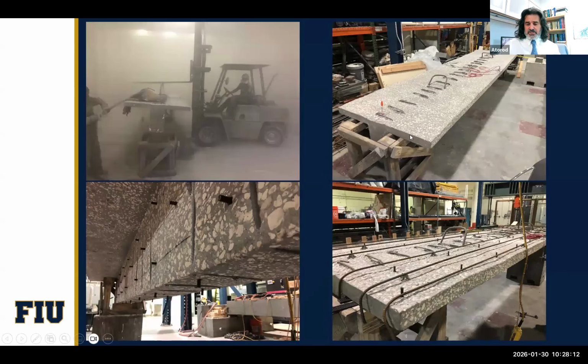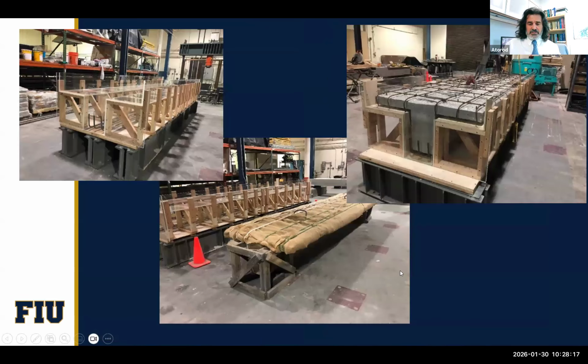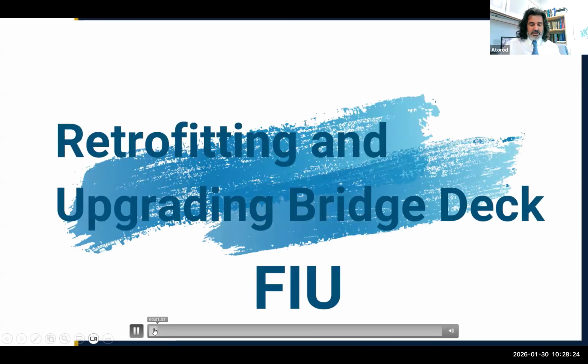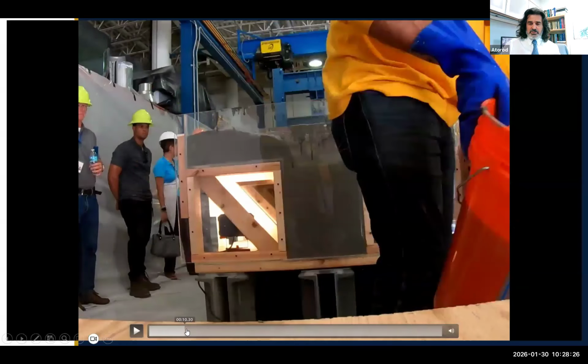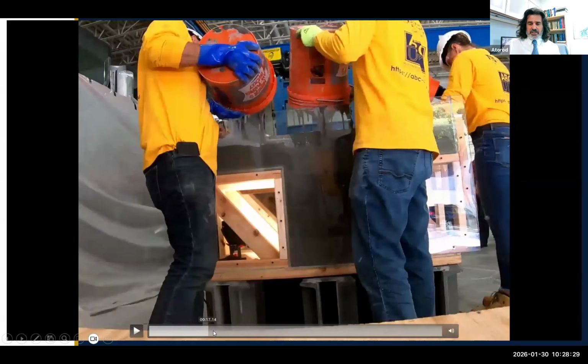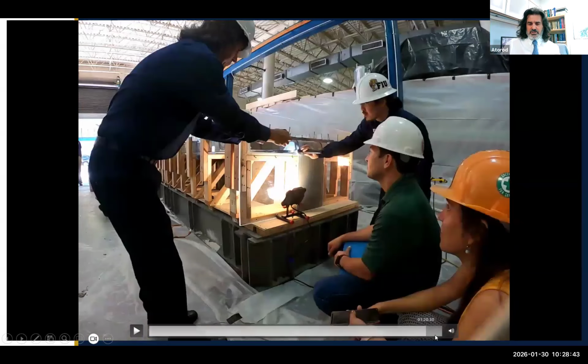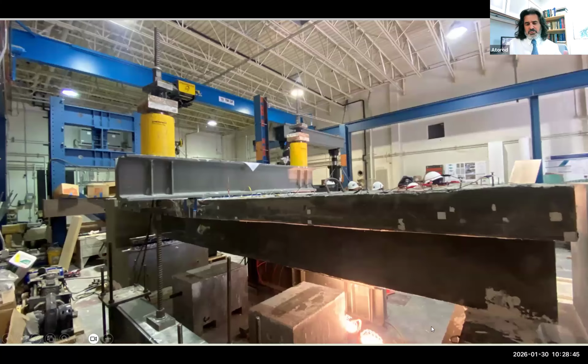Here is the T-beam, and we sandblasted it, put in additional reinforcement, and then put in the epoxy glass formwork. I can show you here: you can see we pour the UHPC, and it flows into a very small area. Because it was a glass formwork, we could see it very nicely. No honeycomb, nothing. You can see how it flows. There's no need for vibration, nothing. And then we tested.